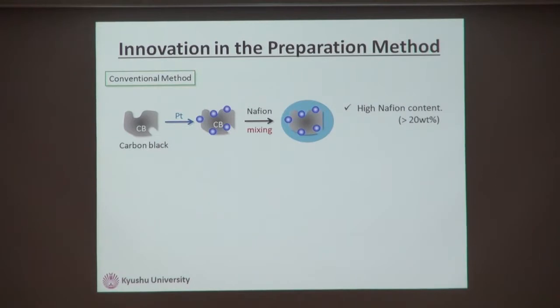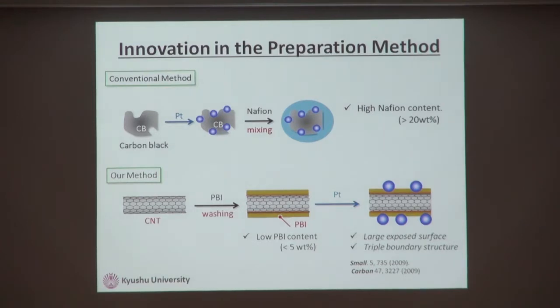So here I show how we compare the conventional carbon black catalyst and our carbon nanotube-based material. For the conventional method with carbon black, platinum is first deposited onto the carbon black surface, and after that, Nafion is added and mixed. This is a conventional fuel cell catalyst. And in our method, carbon nanotubes are dispersed and coated by PBI first, and then platinum is loaded onto the surface of the polymer like this.